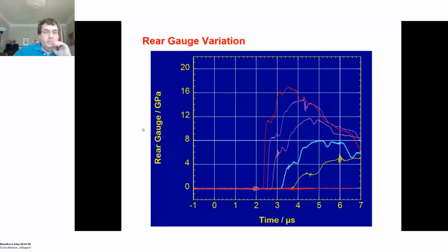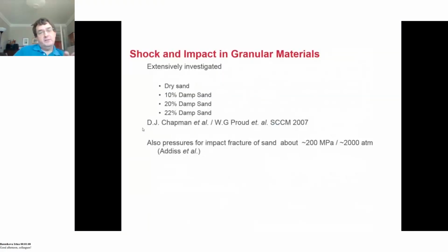So, shock and impact in granular materials extensively investigated. We reported this at shock compression condensed matter for a number of years. We also calculated the pressures for the fracture of sand, that individual grains would fracture around about 200 megapascals. But please remember, a grain in the bed can actually rotate and translate as well as fracture. So there are a number of potential processes that can occur.